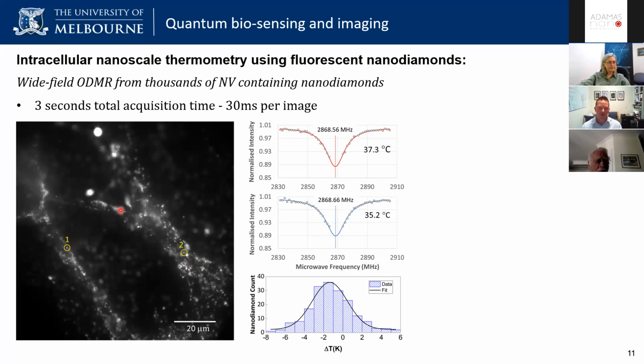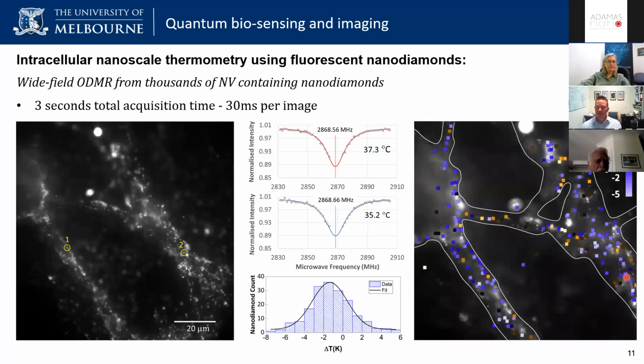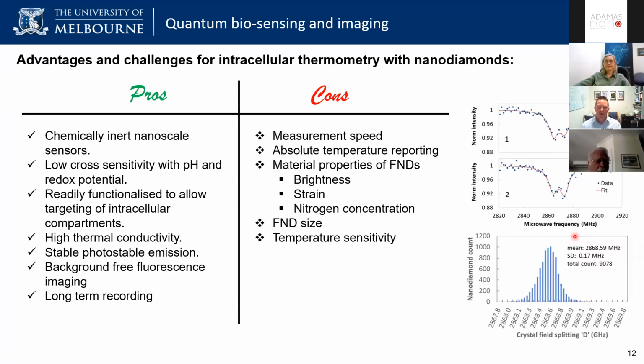And so we did some proof of principle experiments at 37.3 degrees, and then we reduced the chamber to 35.2 and showed that the nanodiamonds were able to report on average that temperature change. And so this was the first time that we could start to then build up an actual temperature map or a temperature profile of that particular system. And so this was the first demonstration of multiple sensing with many, or hundreds in this case, of NV sensors within a living system. So there's certainly prospects for using this sort of technology in different biological systems, but I think there are a number of pros and cons to this particular technology.